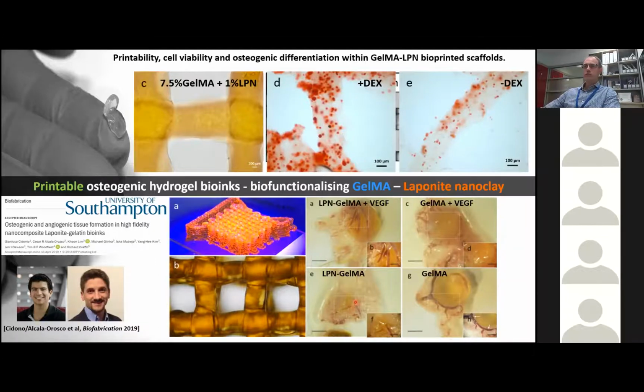Again, in the presence of just straight laponite and GelMA, we could also still see some vessel formation, but in the absence of any laponite, then we did not see penetration. So again, it's providing a very permissive microenvironment. So again, that was interesting to be able to try and see that we can now have, I guess, a multifunctional capability of these GelMA-laponite nanoclays.